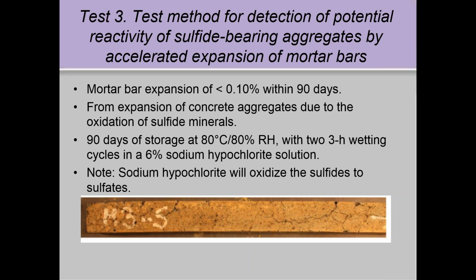So test number 3 is a 90-day test with mortar bars with the crushed aggregate after some cycling in an oxidation fluid. Hypochlorite is just a way of oxidizing the sulfide minerals so that they expand. And you can see the cracking of a mortar bar there where they've had this problem. So it's a pretty severe set of tests, but again, it's to address this issue, which has cost huge money. In fact, the federal government has just put something like $4 million into a research program at Laval University to further work on this issue so it doesn't happen again.